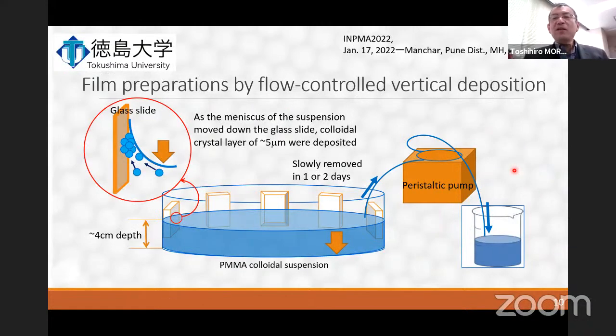For the transmission spectra measurement, we prepared a thin film of PMMA photonic crystal by flow controlled vertical deposition technique. 5 milliliters of the PMMA colloid suspension obtained was diluted with water to a volume of 500 milliliters, which was then poured into a vertical walled glass beaker like this. Glass microscope slides were immersed vertically in the diluted colloid suspension, after which a peristaltic pump slowly removed the colloidal suspension. As the meniscus of the colloid suspension moves down the glass slide like this, the colloidal crystal of PMMA with a thickness of about 5 micrometers was deposited here.